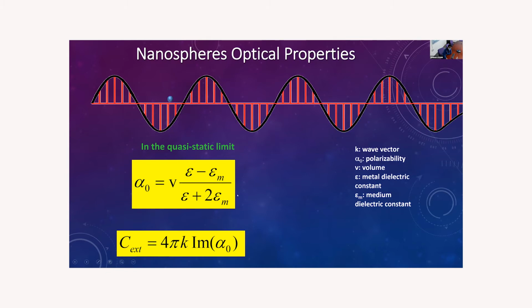So if we take into account these two equations, we can reach the resonant condition, that is that the real part of the dielectric constant of the metal should be equal to -2 times the dielectric value of the media. So it will change if we have the nanoparticle in vacuum, for example, or air, or if the nanoparticle is in water or in a matrix such as silicon.